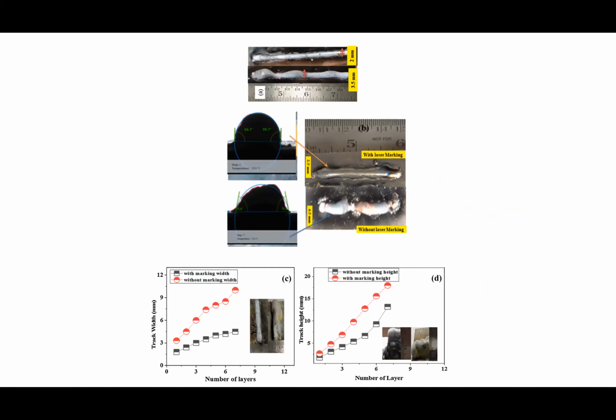Now let us discuss how this effect of laser marking has an impact on the layers with respect to building up of the layers. So for that, we need to investigate the track geometry. The first layer was deposited on the titanium substrate after the laser marking and without laser marking. The roughness and the surface energy will change after the marking, and a track around 1.5 mm deep will provide a path for an unstable melt pool.